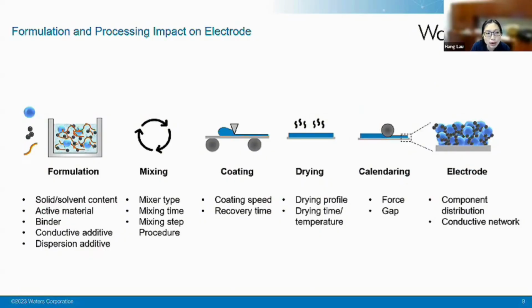But first of all, let's look at what will change your viscosity and the electrode performance at the end. Your formulation, how much solvent or solid content is in the slurry, will really dictate the viscosity of the material. Your binder, active material, cathode, and solvent content. Sometimes people may add a dispersant to the material. That also impacts how well the materials disperse in the slurry. Mixing: the type of mixer that you're going to use, planetary mixer, solid mixing, and how you make the procedure. Do people do pre-mixing, dry mixing of the material first? The procedure and the mixing time will impact your ultimate formulation and the slurry consistency.